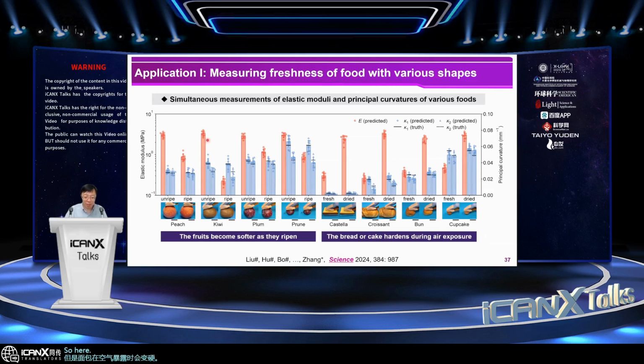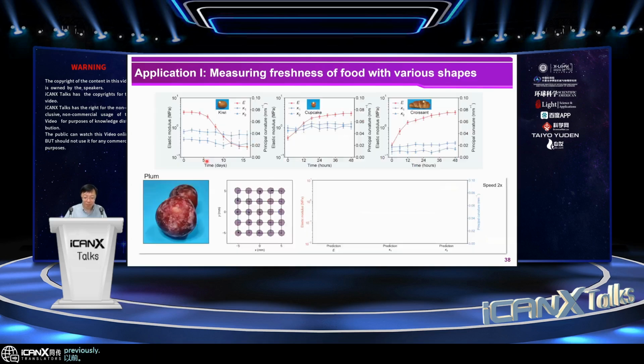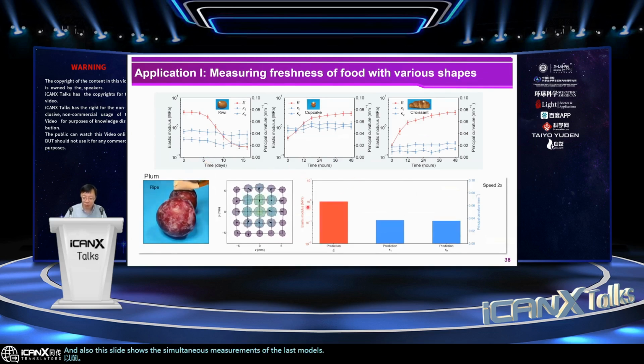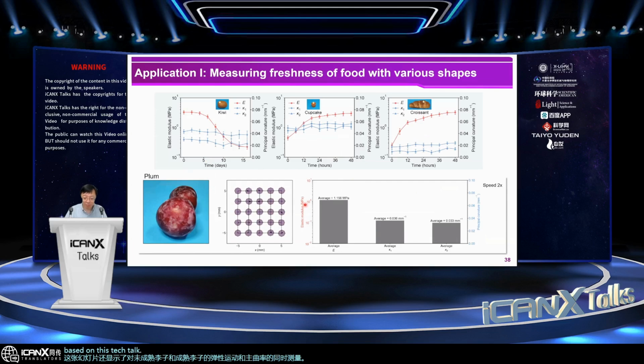So here, in particular, for the kiwi, the elastic modulus in the ripe state could be around 10 times smaller than the modulus in the unripe state. So this information was unknown previously. And also, this slide shows the simultaneous measurements of the elastic modulus and principal curvatures of an unripe plum and a ripe one based on this tactile system.